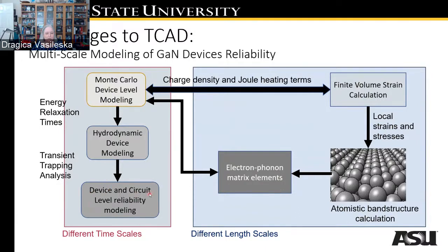If we're interested in, for example, a device and circuit level reliability modeling, we have to abandon Monte Carlo device models because we can do with Monte Carlo something in the range of a fraction of a nanosecond time scale. If we are interested in larger time scales, then bulk Monte Carlo results can provide the energy relaxation times, which are used in hydrodynamic device modeling, with which we can do milli or microsecond modeling. If we want to model transient trapping analysis, then we need to do reliability modeling.